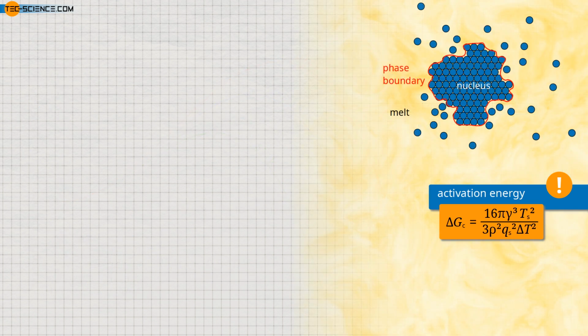As already explained, the activation energy is provided by thermal fluctuations in the melt. Several small fluctuations are more likely than a single large fluctuation. This explains why the number of nuclei capable of growth increases as supercooling progresses. Strong supercooling is therefore usually desirable, as it leads to a fine-grained microstructure that is characterized by high toughness and strength. However, there are limits to the increasing nucleation rate with increasing supercooling.